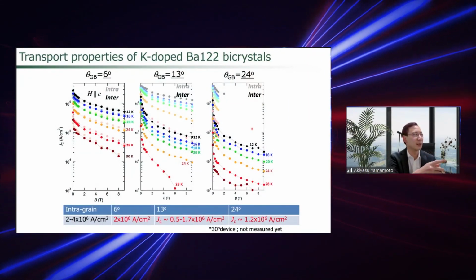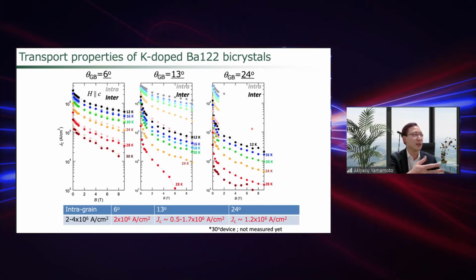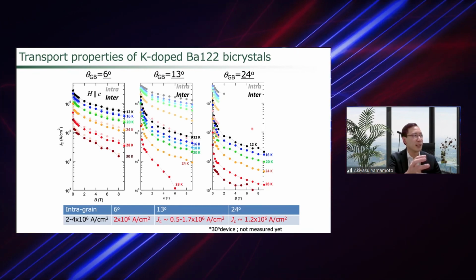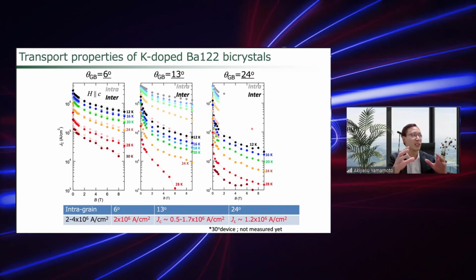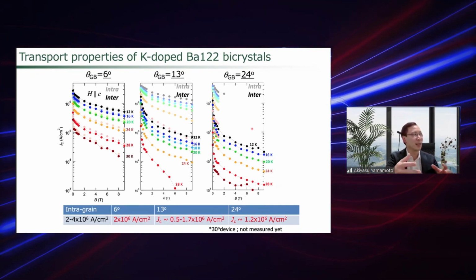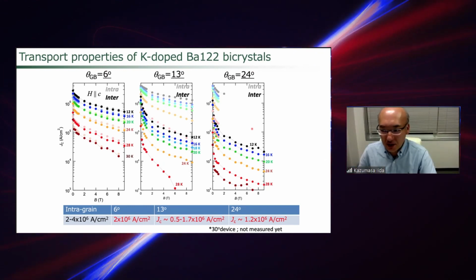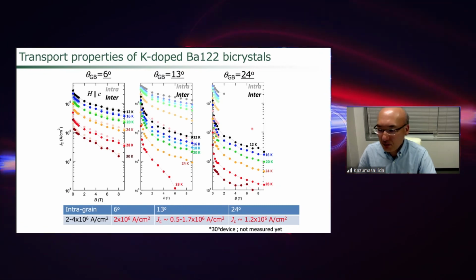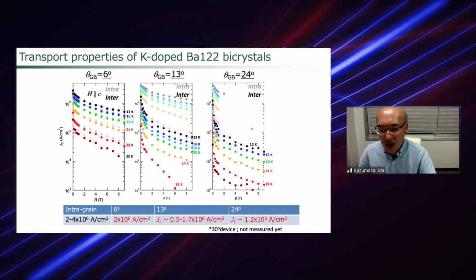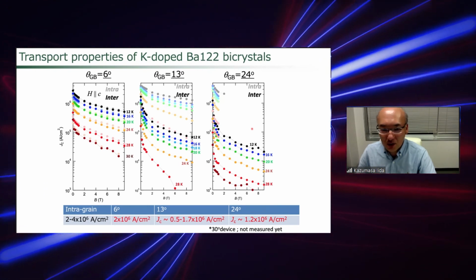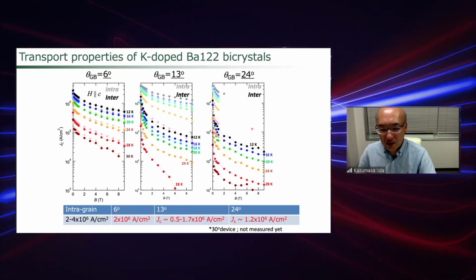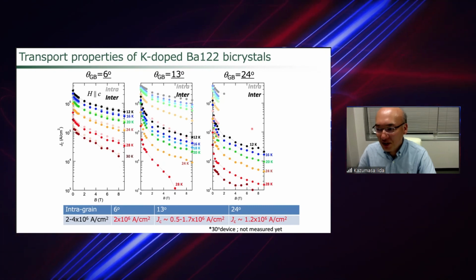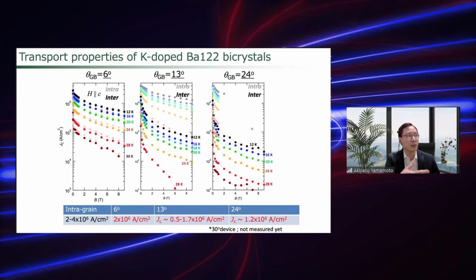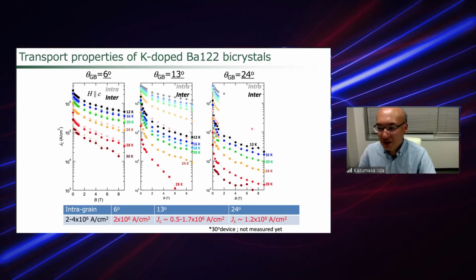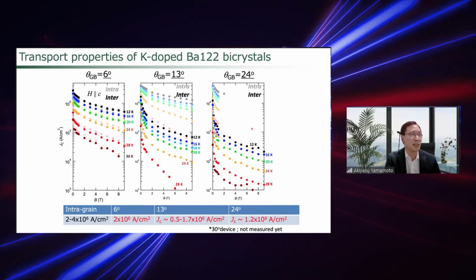Actually, I have one question. If we look at this slide, it is quite interesting to see that the grain boundary Jc, the intergranular Jc, is sometimes higher than the grain Jc. Do you have some idea about this? Yes, I think it's some kind of grain boundary pinning, especially for the low field, and this is also sometimes observed in films grown on the technical substrate. Is it also observed in YBCO? Yes. Okay, thank you. Are there other questions?